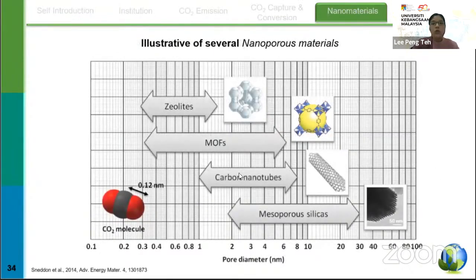So this slide shows you several types of nanoporous materials. Over here, we have zeolites, MOF (metal organic framework), carbon nanotubes, and mesoporous silica. Many of these materials, for example the carbons, the nanotubes, and also the silicon-based materials, are thermally stable up to around 200 degrees C. These properties are very important for post-combustion CO2 capture.